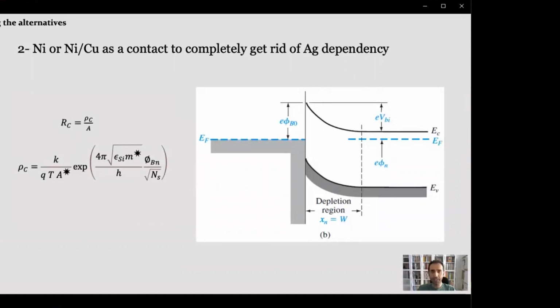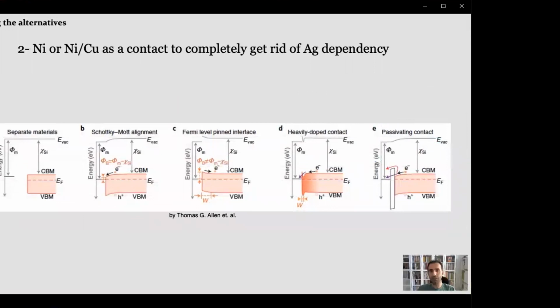So increasing the doping concentration underneath the contacts can help decrease the contact resistivity and reduce the Shockley-Read-Hall recombination. So that's why it can help the performance of a solar cell. There's also another way to improve the performance of the cell, that is passivating contacts. This features a thin film between the contacts and silicon layer, usually silicon dioxide or hydrogenated amorphous silicon. This layer in between that you see here acts in a way that the semiconductor surface potential can be influenced by the overlying contact material, facilitating tunneling or thermionic emission through the contact structure.